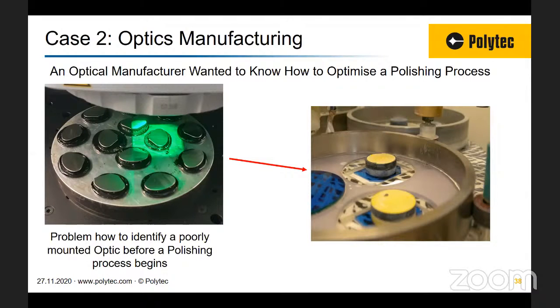So you can see what we have here is some ground optics mounted on a polishing block, and they're attached through bitumen. So what happens is you have a mounting block, you have a fixture, you have your optics, you then heat up the block, you place the optics on through a masking tool, they're then pressed down, and then you take these pre-ground surfaces and you polish them flat.